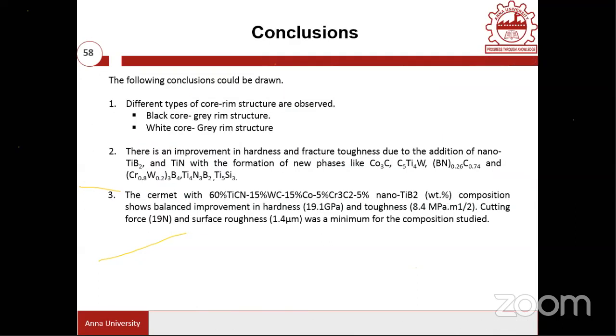So from that, I can say that by modifying core rim structures, one can even play with the microstructure modification, and you can change the hardness and toughness values. And the new phases formed by the addition of TiB2 and TiN are responsible for improving the hardness as well as the toughness value. And the CERMET with this composition, 5% nano TiB2, has a balanced improvement in the hardness value, 19.1 GPa hardness, and toughness 8.4 megapascal root meter.